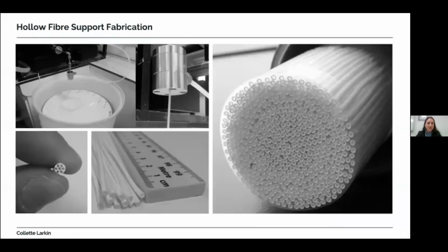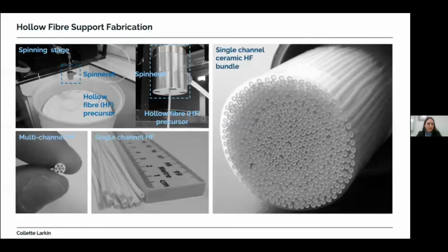These photos are a snapshot of the hollow fiber support fabrication process used to create ceramic hollow fibers and show what the hollow fibers look like. The hollow fiber support for the hollow fiber adsorption unit was fabricated by phase inversion, followed by sintering at high temperatures. The phase inversion process takes place during the spinning stage of the hollow fibers and produces a hollow fiber precursor, which can be seen leaving the spinneret. The hollow fiber precursor is then placed into an oven at temperatures of around 1400 degrees Celsius to complete the sintering process, giving the final ceramic hollow fiber support. For our work, we used alumina hollow fibers. And the remaining photos are of a multi-channel hollow fiber and single-channel hollow fiber that I've just included for your information, so you can see what different variations hollow fibers can look like.